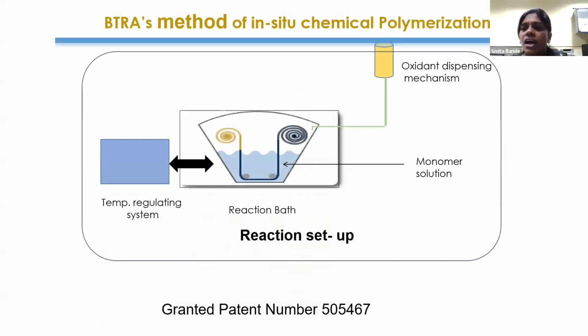For woven samples, we have done the coating using the simple jigger dyeing principle. Here we wound our fabric over 2 rollers of the jigger machine and allowed it to undergo the monomer treatment first. Then in the same bath, we added the oxidizing agent in a controlled manner and allowed it to undergo polymerization. Within 3 to 4 hours, the polymerization completes, and then we can remove the sample, wash it in water and dry it in atmospheric air. That conducting fabric, formed with the conducting polymer coating, can be characterized for conductivity measurement and so on.